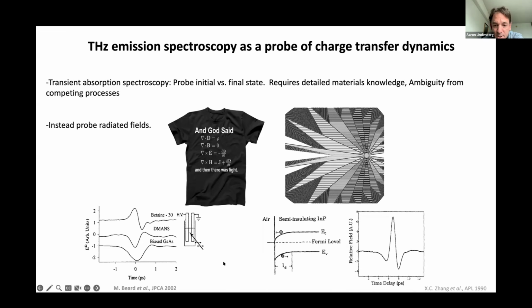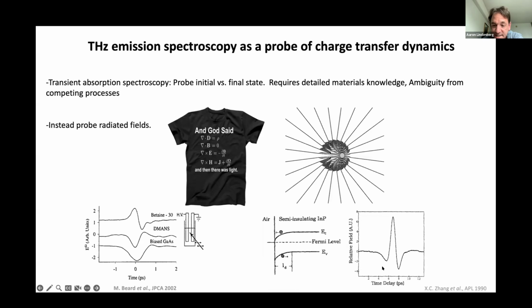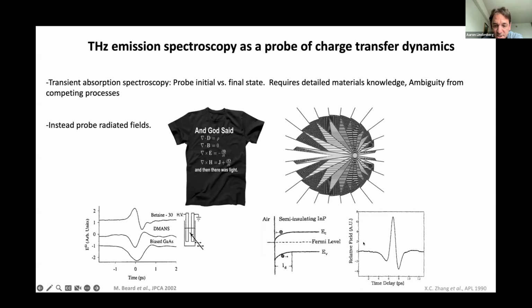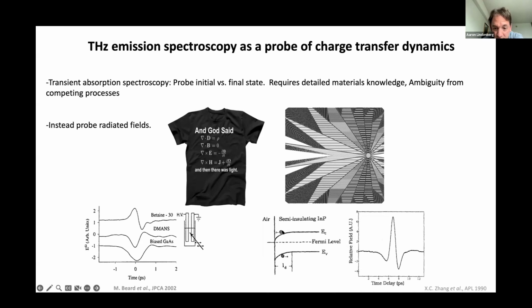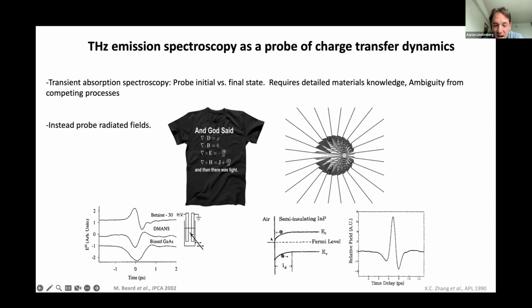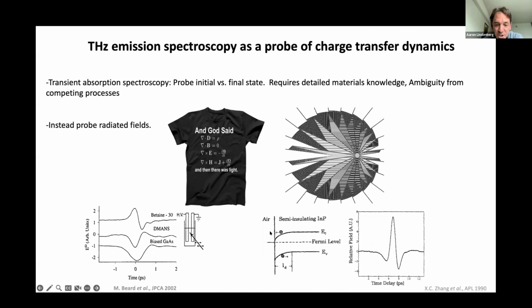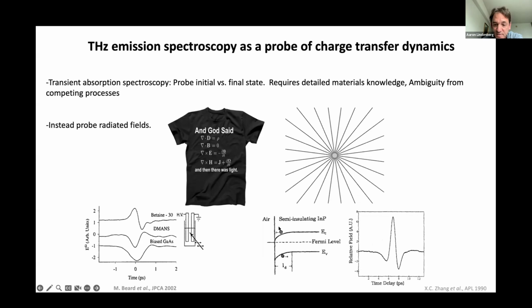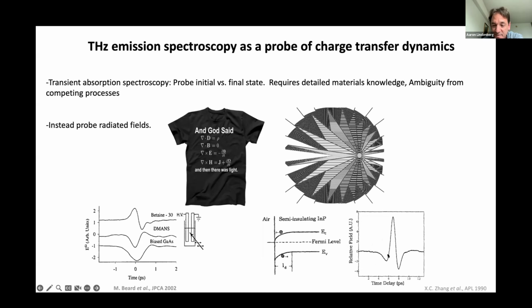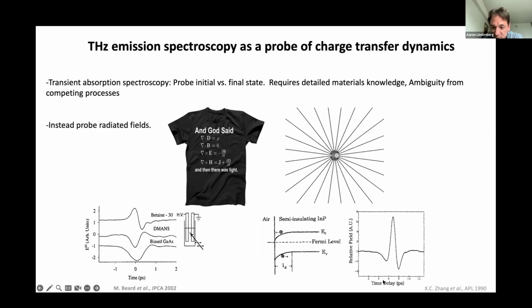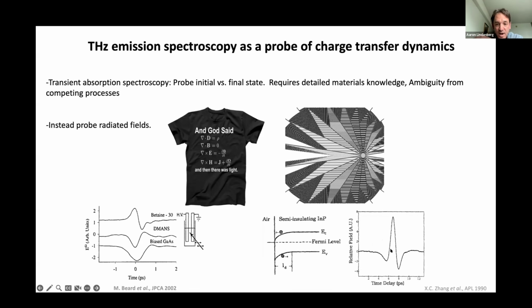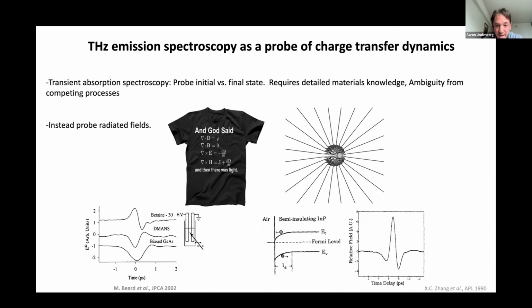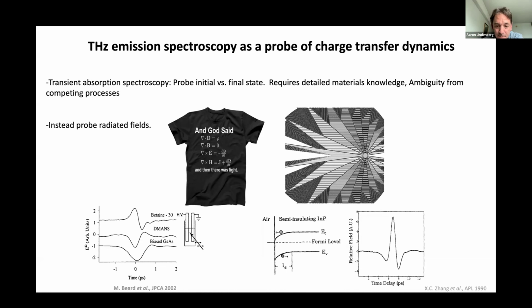There have been many examples of this, even dating back to 1990. I think this might be one of the first examples, probing band bending at an interface under photoexcitation. Charges move in this interfacial field and give rise to a single cycle electromagnetic field pulse. The Fourier transform of this pulse as a function of time gives you a frequency spectrum, which is peaked at frequencies of order 1 terahertz, something like that.